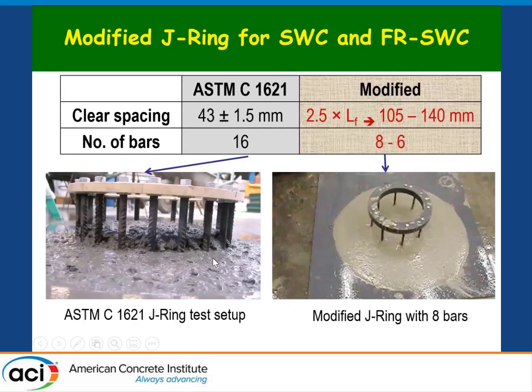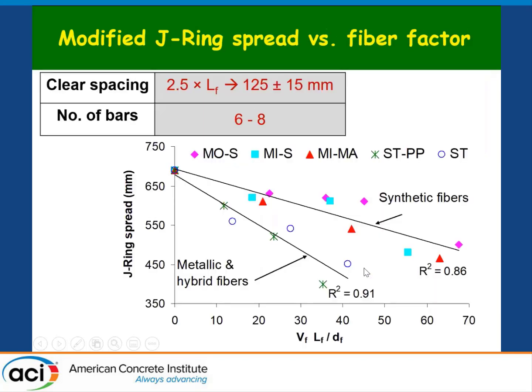But when it comes to passing ability, Joe showed the U box, but you have the L box, you have the J ring. With fibers, there are a lot of issues, and we felt that the test is really not very adapted to using fibers. So we tried to increase the gap between the rebars to about 2.5 times the length of the fibers, and that gave us, depending on the fiber length, instead of 16 bars, 8 bars, or in some cases 6 bars.